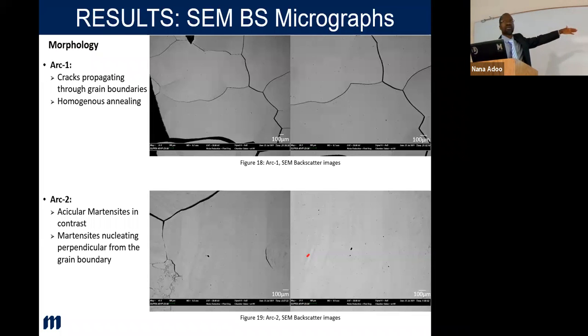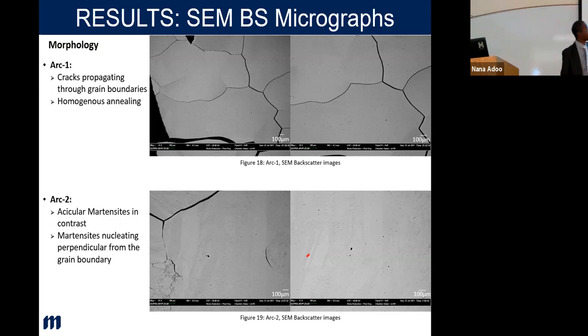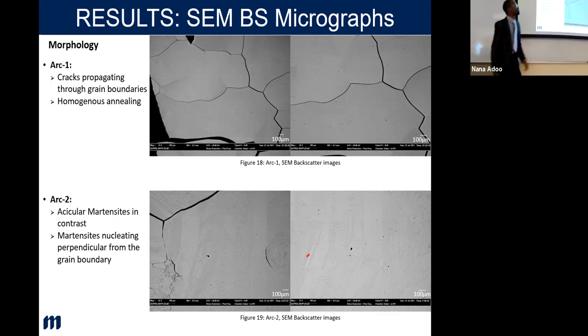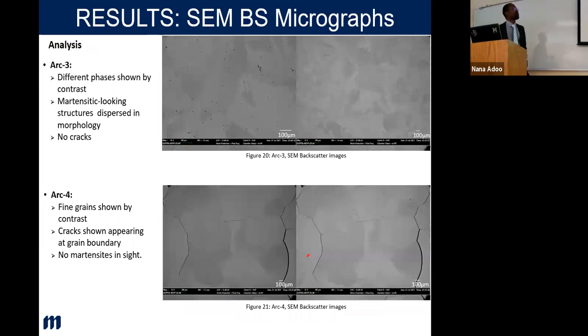But when you come to the second arc melt, you could see these martensites showing in there. You could see those acicular structures. You could see them from the grains going there, but never guaranteed any transformation. 3 had these grain texture. It did not actually show just like the annealed sample, but there was no transformation as well. And then at 4, which transformed and produced better results, did not also show those martensites. Of course, we don't expect to see it at this temperature unless we subject it to subcooling to see those structures forming here and see it.